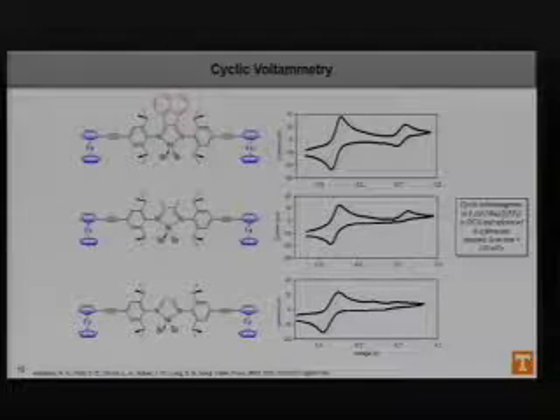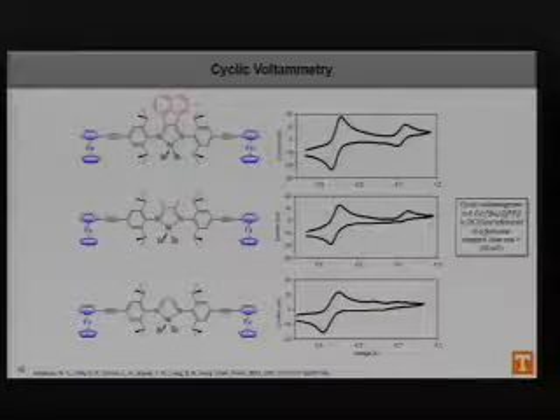So then we moved on to cyclic voltammetry to try and see if these had oxidation and reduction potentials. And sure enough, every one of them actually has a peak that corresponds to the ferrocene that's in the backbone. However, only this acenaphthoquinone backbone shows a reduction potential, which is what we would expect, because these backbones aren't large enough to stabilize the additional electron that we would be adding to the system.